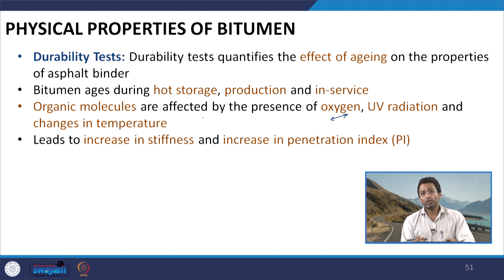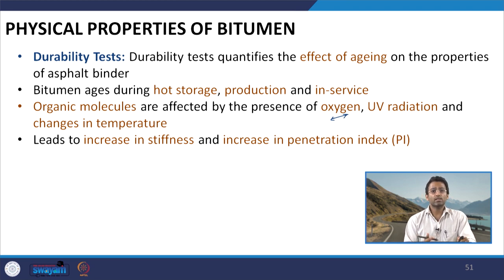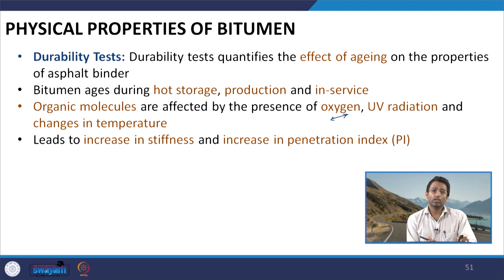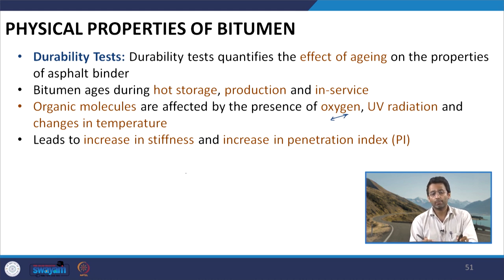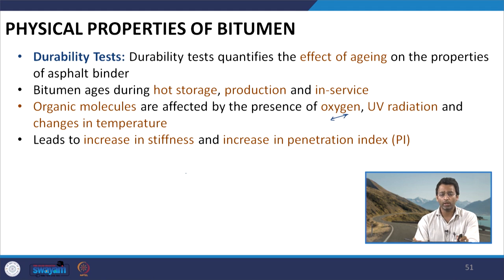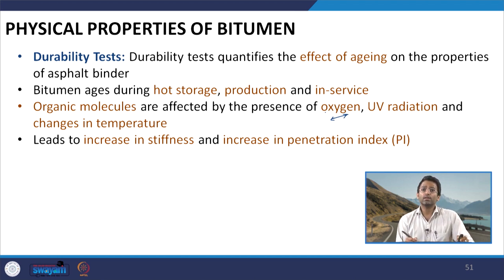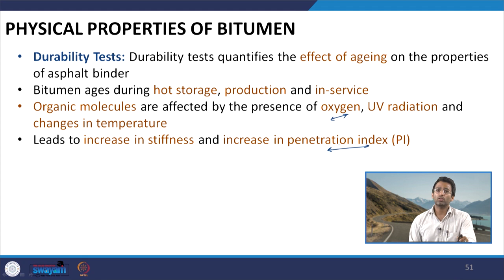Because of oxidation, UV radiation, or temperature changes, the stiffness of the bitumen increases. After aging, the penetration of bitumen gets reduced and the viscosity and softening point increase. The extent of this change depends on various factors including the type of bitumen. Aging also increases the penetration index, which indicates the temperature susceptibility of bitumen, as discussed in previous classes.